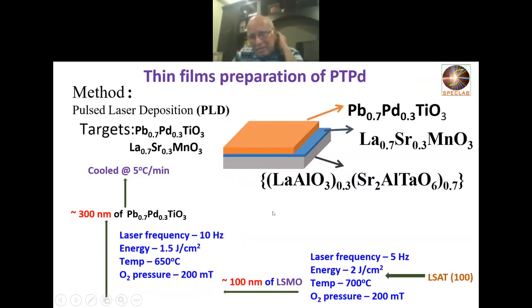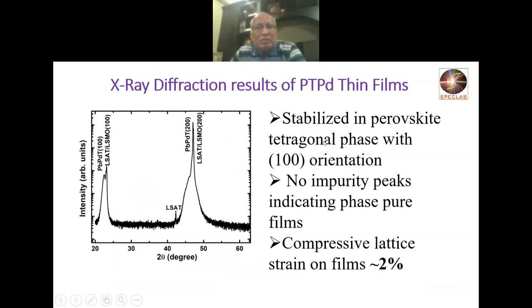Encouraged by our ceramic data, we decided to make thin films of this material. The thin films here are lead titanate along with Pd 30%, and the substrate was LSAT, with a bottom electrode of LSMO. This is by pulsed laser deposition, so these are the growth conditions. The thin films stabilized in the tetragonal perovskite phase, of course. There were no impurity peaks, indicating phase pure films. And the compressive strain was something like 2%.